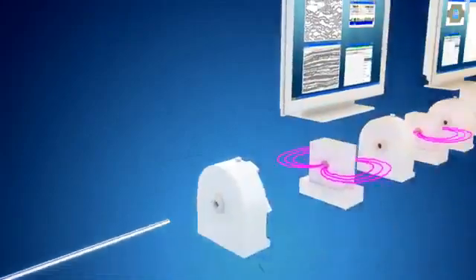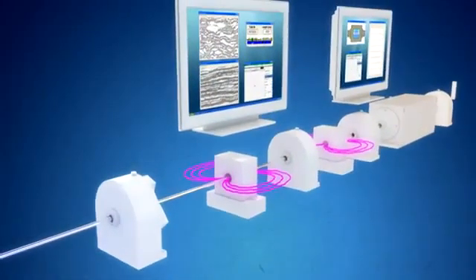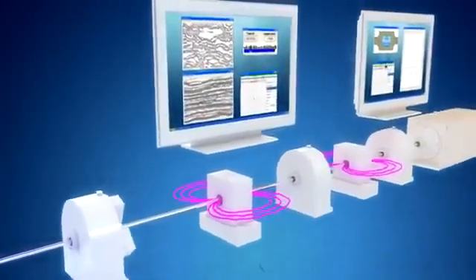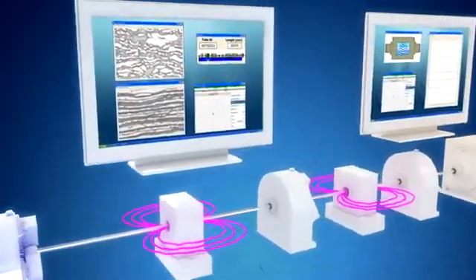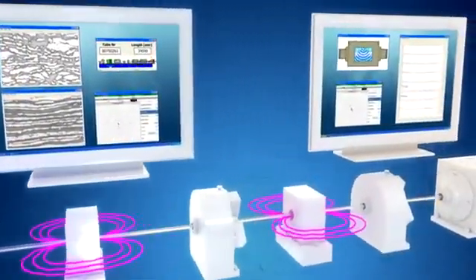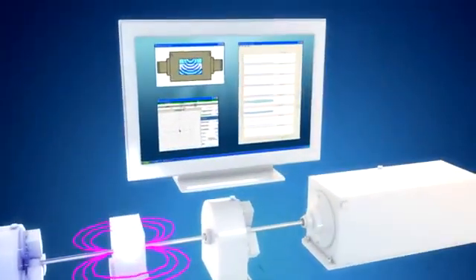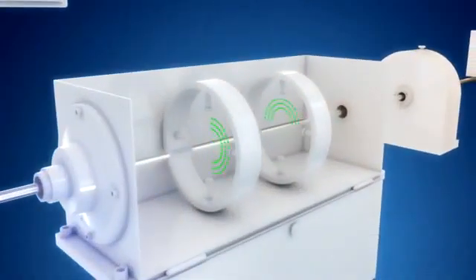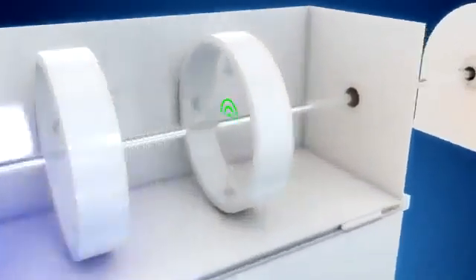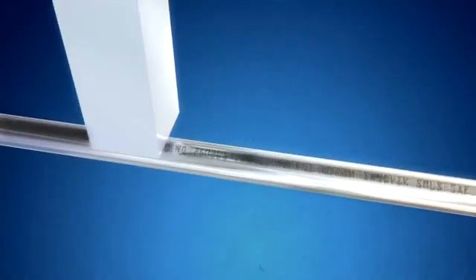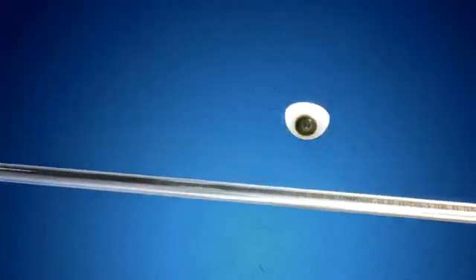According to customers' requirements, the tubes are fully inspected for defects using ultrasonic and eddy current testing methods set to detect the tiniest defects such as cracks, cavities, or other material defects that the naked eye can't detect. Their dimensions are verified and they are also checked to ensure they are free of intermetallic phases. This is followed by visual inspection.